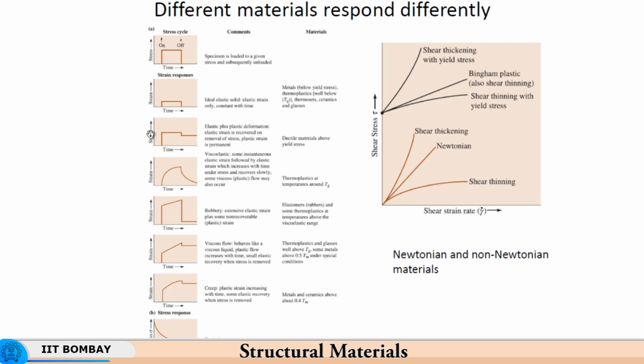You need to therefore make sure that your product is designed sufficiently well, so that the stress coming on the product in service is well below the yield strength of the material, so that in service the material does not yield. So, in case of a boiler, the in service condition is certain temperature and certain pressure inside. Naturally the boiler plate should be sufficiently thick, so that the maximum stress generated in the boiler plate is much lower than the stress that is required for permanent deformation of the boiler plate at the service temperature.